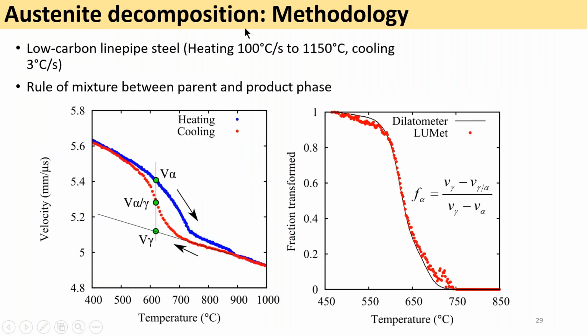So moving on to the austenite decomposition this time, in red here you've got the cooling curve, and the cooling curve shows a sharp transition that can be utilized the same way as we use the dilatometry curve to measure the austenite fraction upon cooling. This method uses a simple lever rule, where we have the velocity in austenite minus the velocity in the two-phase region, divided by the difference in velocity between austenite and ferrite. So you have the velocity here in austenite, the velocity in ferrite here, and by using this relationship, we have a very good correlation between dilatometry and Lumet measurement for the austenite decomposition.